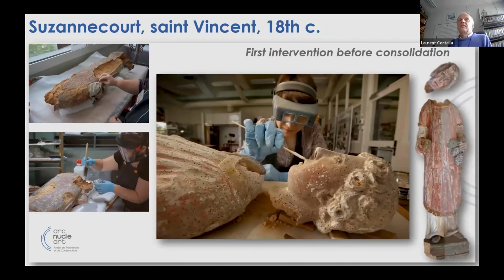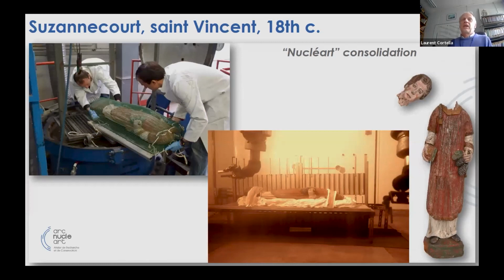So you can see the preparation, the first intervention before consolidation, we have to clean. This is not a COVID test, this is just cleaning. And then the impregnation, we have a tank of 3,000 liters, in which we can make first vacuum, then pressure. And then we put the sculpture under irradiation to harden the resin. And we have all the different pieces that are hardened.